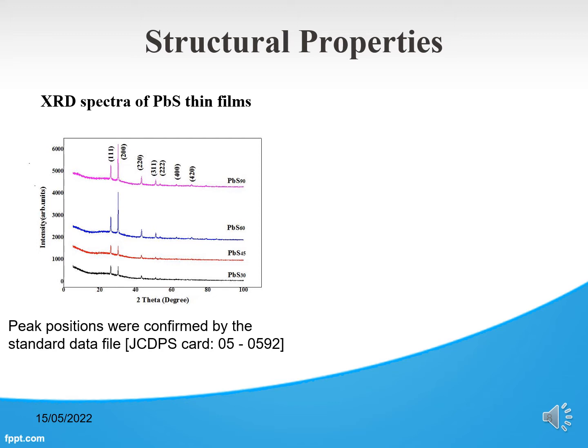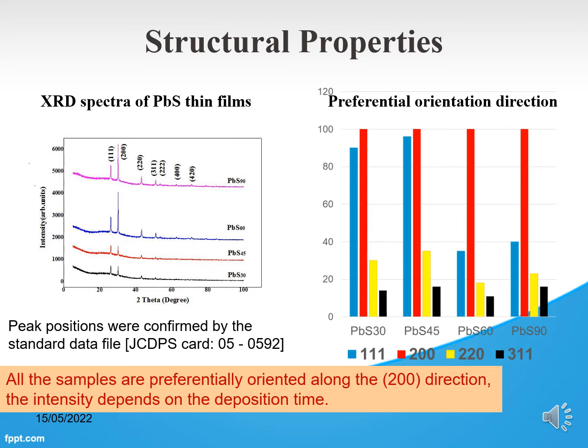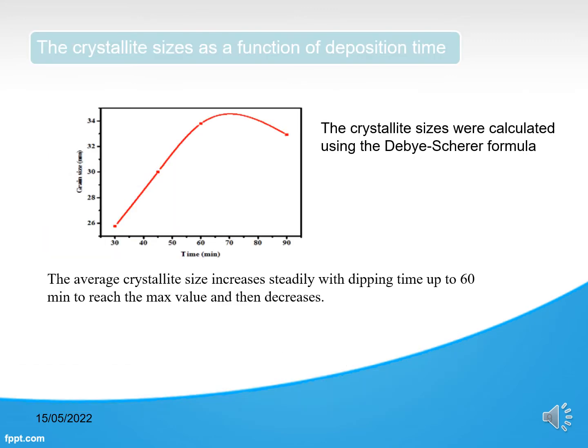As the deposition time was increased, a clear evolution of multiple peaks was observed, indicating the polycrystallinity of the films. Preferential orientation direction. All the samples are preferentially oriented along the 200 direction. The intensity depends on the deposition time.